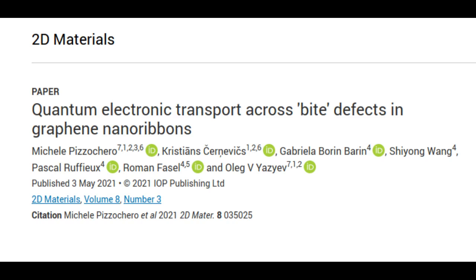The paper Quantum Electronic Transport Across Bite Defects in Graphene Nanoribbons, recently published in the journal 2D Materials, specifically looks at 9-atom wide armchair graphene nanoribbons, 9AGNRs. The mechanical robustness, long-term stability under ambient conditions, easy transferability onto target substrates, scalability of fabrication, and suitable bandgap width of these GNRs has made them one of the most promising candidates for integration as active channels in field effect transistors, FETs. Indeed, among the graphene-based electronic devices released so far, 9AGNR FETs display the highest performance.